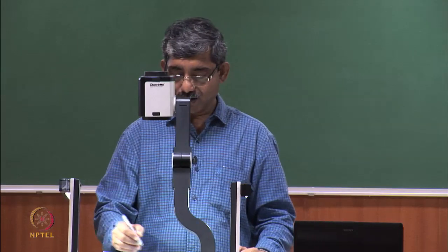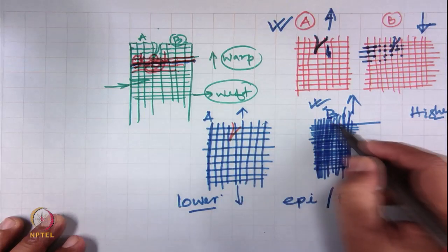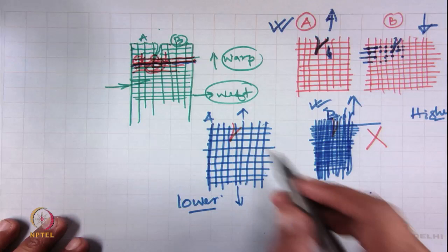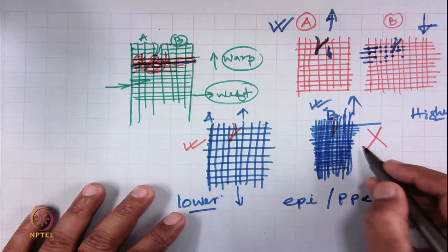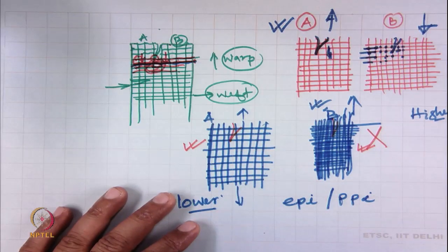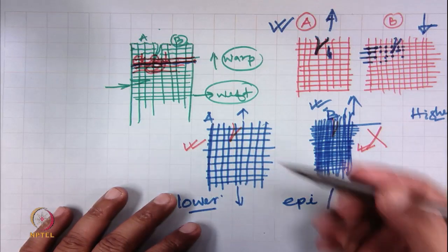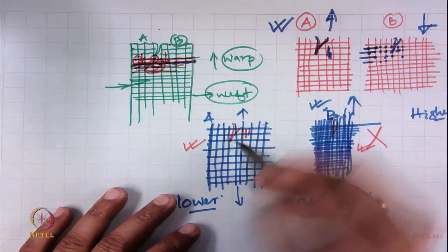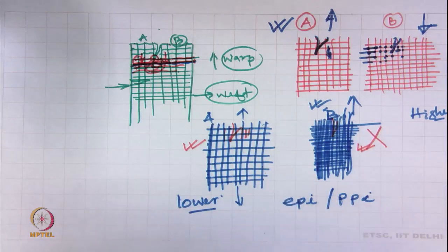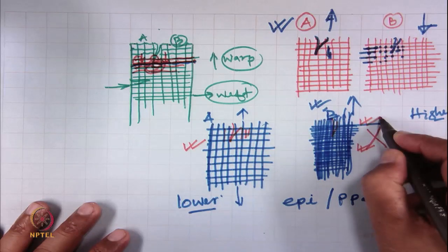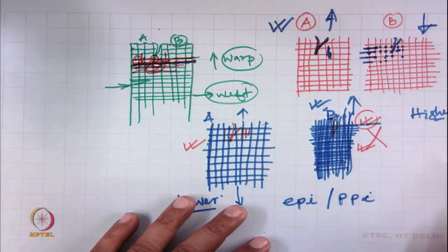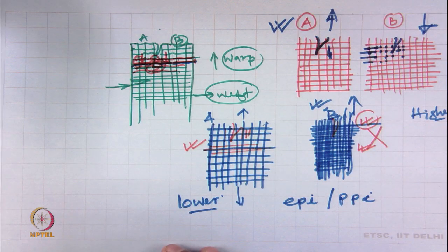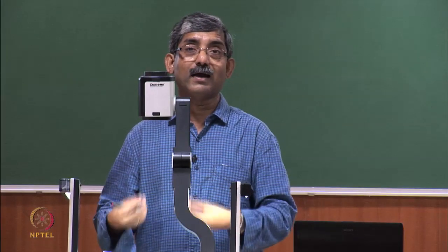But if we test for tear strength, this fabric will fail, and the open structure fabric will have higher tear strength than this closed fabric, although they are made of the same warp and weft yarn. And again the reason is that here the sliding takes place, because of the open structure the threads will slide and they will have the chance of accumulation. So, in compact fabric the threads break sequentially one by one, but here before breaking, they actually accumulate and ultimately the tear strength is higher. So, that is a common phenomenon, a fabric with open structure will have higher tear strength.